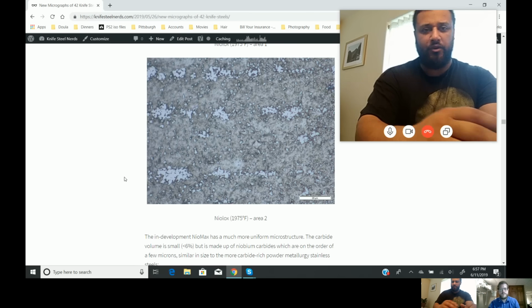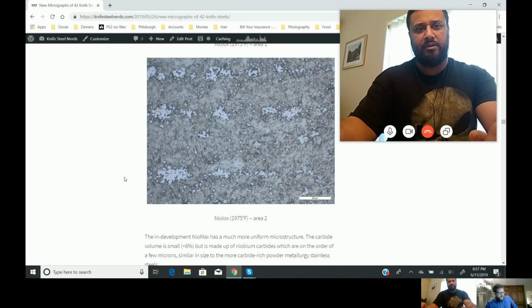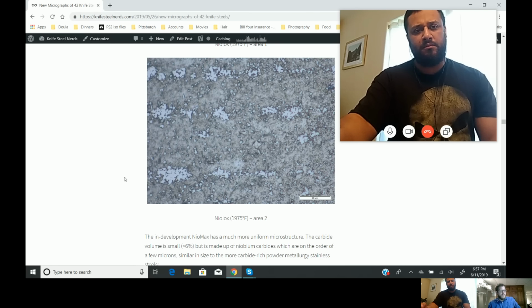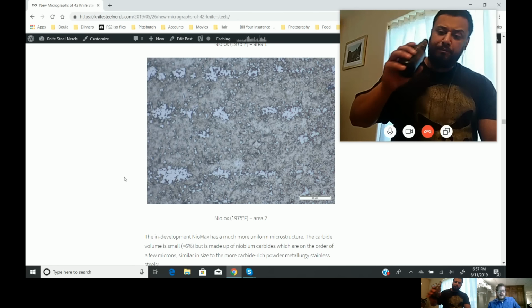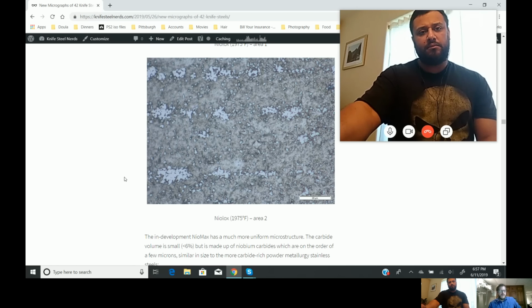Are these like vanadium enhanced chromium carbides? I remember you touched on that with your CATRA testing article about wear resistance. Yeah, there's probably some vanadium in the chromium carbide, which can increase the hardness of those chromium carbides a little bit for better wear resistance. So the top of the scale is vanadium carbide. They're the hardest. Next is niobium carbide, which is a little bit softer. Okay. So those are the ones you want for really high wear resistance. And then below that is vanadium enriched chromium carbides. Then there's a couple different types of chromium carbides, and the M6C, those high-speed steel moly tungsten carbides, they're kind of around the same area as a chromium carbide. And then well under that is iron carbides called cementite. And those are not much stronger than steel. So they don't contribute to wear resistance as well as a vanadium carbide.